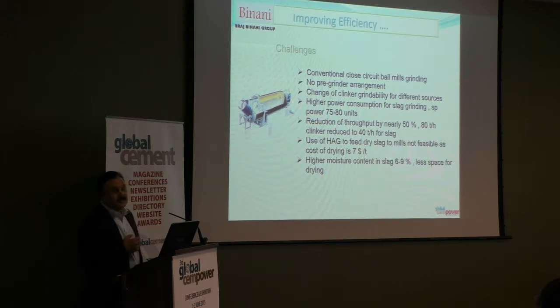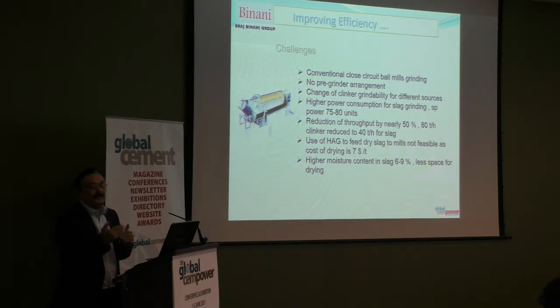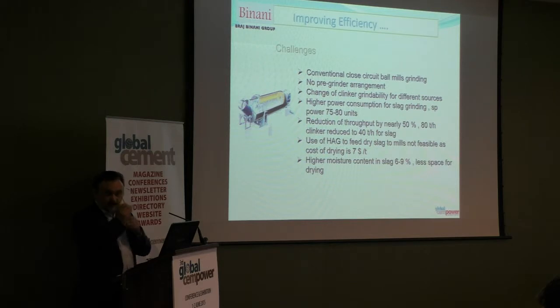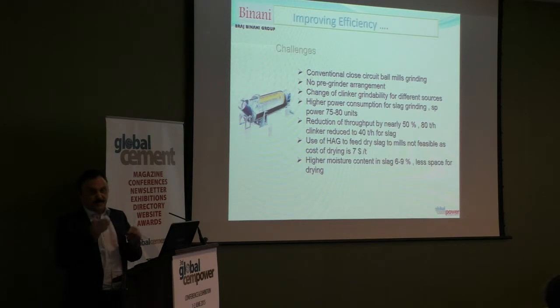All of them are conventional closed circuit ball mills. You have a limitation. There is no pre-grinder arrangement as on date. Then, being a standalone grinding unit, clinker grindability will change. The moment you change your source, you will have an impact on clinker grindability. So if you have a mill which is giving 80 tons per hour, change the source, it may come down to 75. So day in and day out, you have to live with all these kinds of challenges.